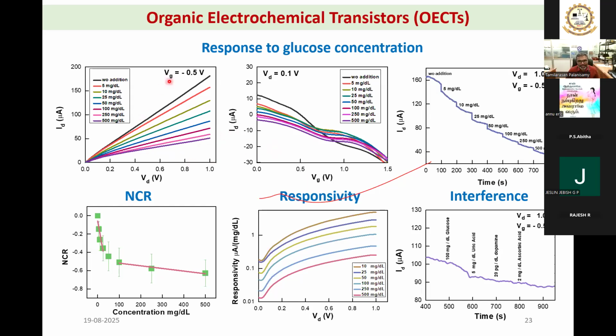Okay. And the same changes are observed in the transfer characteristics also. And the extracted values are given here. You can clearly see when you increase the concentration, you are actually seeing the decrease in ID, the drain current. In this device, we repeatedly seen that this slope, actually it was supposed to be a clear step, but we have seen a slope. So that's why we have used this IV characteristics, which is more stable for subsequent analysis.